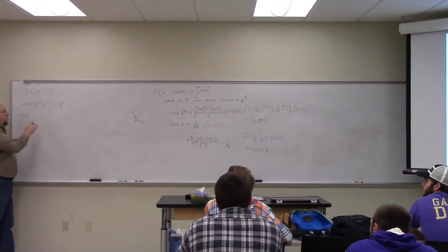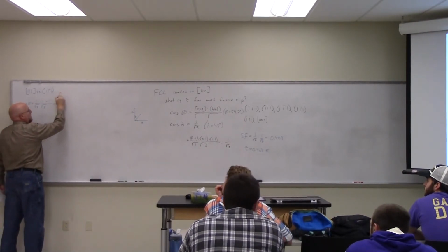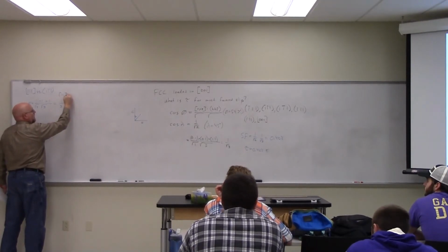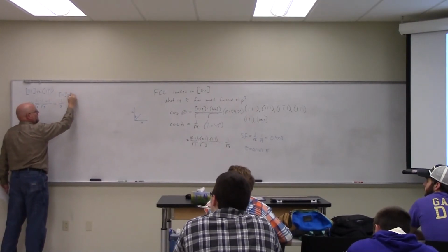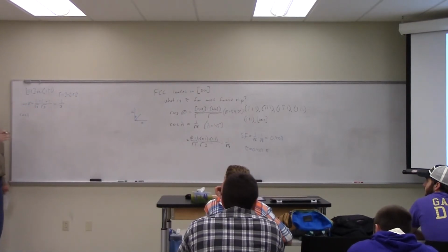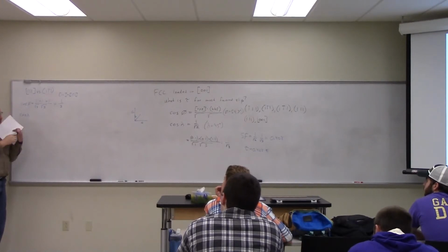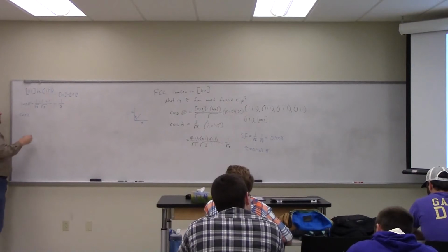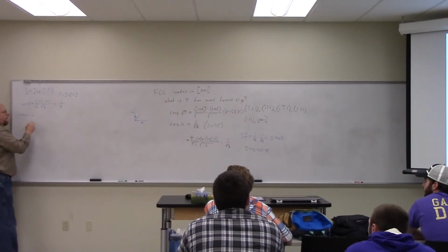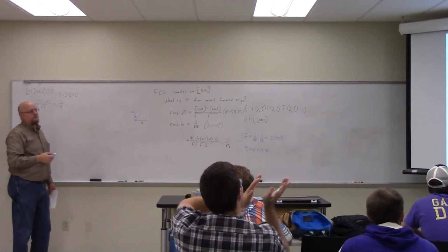Right, so what we're comparing here is the dot product between the 1, 1, 1 direction dotted with the 1, 1 bar 1 direction, because we dot it with the direction perpendicular to the plane. And then lambda will take into account the direction in the plane, right? So what is the direction in the plane? Pick one.